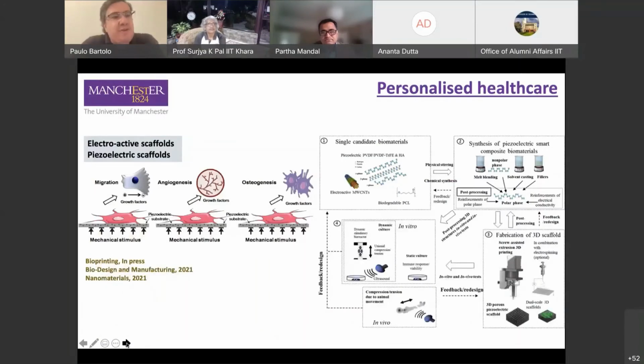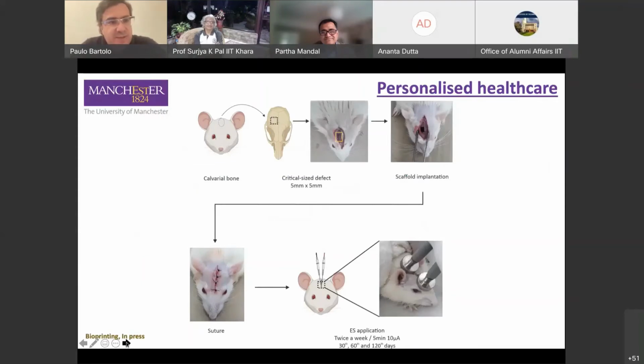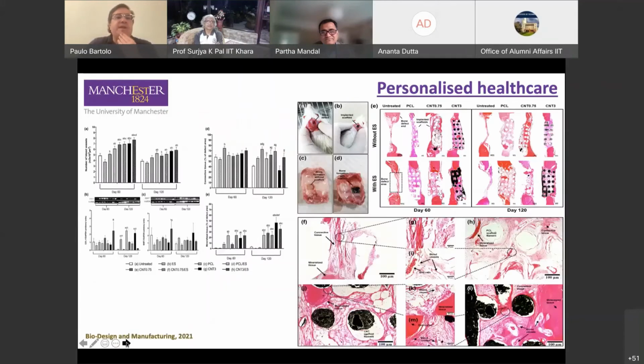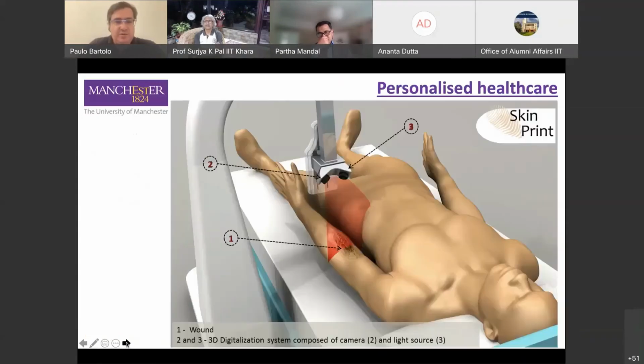Right now, we are trying to mimic the nature of bone. Bone is a piezoelectric material, but it has also a reverse piezoelectric effect. We are mimicking it by developing electroactive scaffolds and piezoelectric scaffolds. We have done extensive work regarding electroactive scaffolds using graphene and carbon nanotubes. Sorry for the next image because it shows some animals and some blood. We tested these scaffolds together with the application of external electrical stimulation, and we obtained very promising results, showing that the combination of our scaffolds together with the external electrical stimulation not only stimulates new bone formation in a more organized way, but it was also possible to observe the formation of the vasculature system, which is critical in the case of bone.